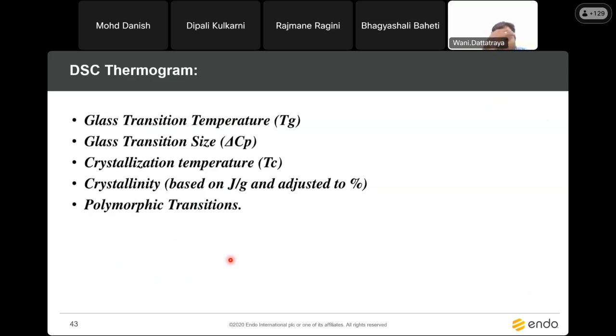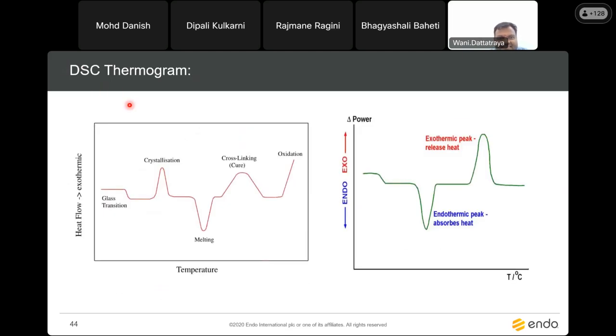So a DSC thermogram mainly consists of the glass transition temperature, glass transition size, crystallization temperature, crystallinity, and polymorphic transition. This technique is mainly used for polymers. So this is generally how a DSC thermogram looks. First is the glass transition temperature. Then you will get some crystallization. If your molecule is crystalline, then you will get the melting-related thermogram. If your molecule is amorphous, you will not get this melting-related endothermic peak here. So this is the exothermic or endothermic peak. Like this, you will get the thermogram in your DSC.